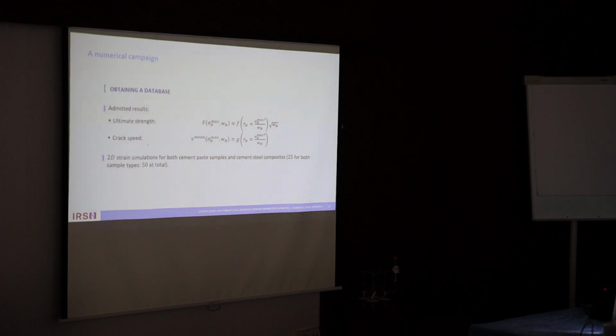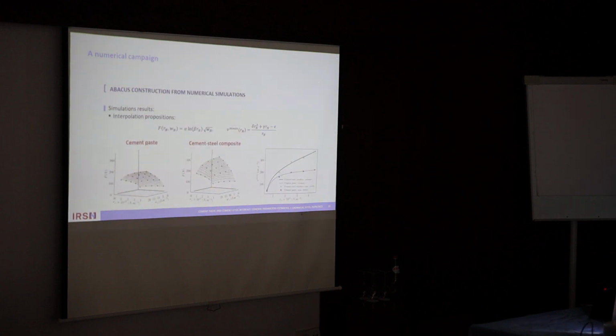So I have carried out 2D strain simulations for both types of samples, 25 for both types, or a total of 50 simulations, in which I choose particular values of cohesive mode parameters close to expected ones, and the resulting data, the ultimate strength and an average crack speed developing on the sample, have been associated to the used cohesive parameters. So here are the results.